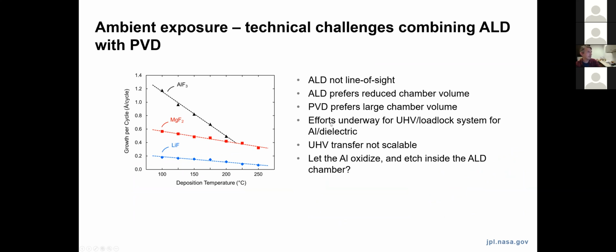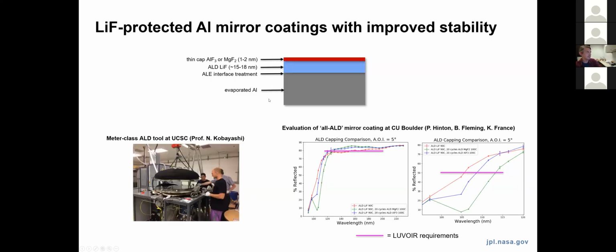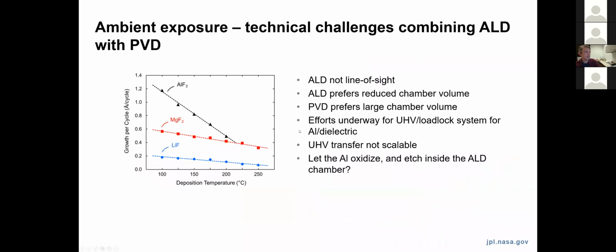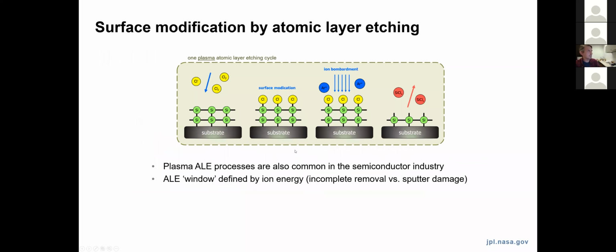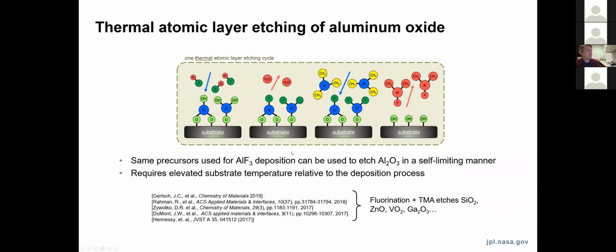It's implied on the last slide that we have this issue here where although we're creating all of these protective coating layers with atomic layer deposition, there's actually not a good way to deposit aluminum with ALD. So the aluminum layer is still evaporated. It's technically challenging to consider combining these two techniques for various reasons. So to cut to the chase, we've been using a process called atomic layer etching to allow us to combine evaporated aluminum for now with these ALD encapsulation layers.